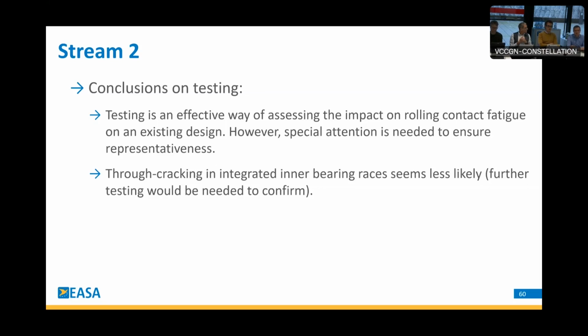some results that really we could not explain. There were some samples that sometimes will crack through rather quickly. Sometimes they will only spoil, and this is something that it's difficult to explain. But at the same time, we found some samples that seem to behave a lot better and to provide repetitive results, and also more importantly to, let's say, behave more in line to what the simulations were predicting. So that is just to say that, okay, it's possible to test, but it makes no sense to just prepare a specimen and put it into a bench with some kind of damage and just run it to see what happens. You really need to make sure that what you're doing is actually going to represent your design properly.